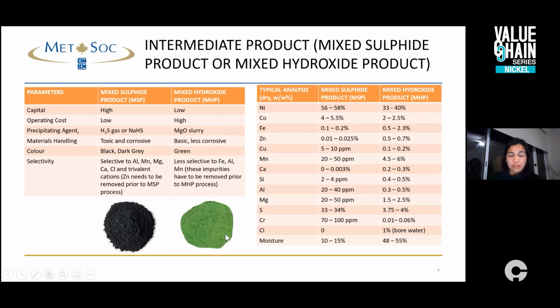And like I mentioned earlier, mixed sulfide is very selective to a number of impurities, producing a much cleaner intermediate compared to mixed hydroxide, particularly with iron, one of the major impurities and hard to remove downstream. As a side-by-side comparison with typical analysis, we can see that the mixed sulfide product contains a lot more nickel per ton of precipitate compared to a mixed hydroxide product.